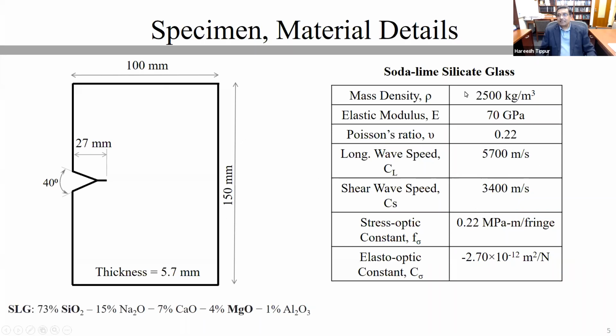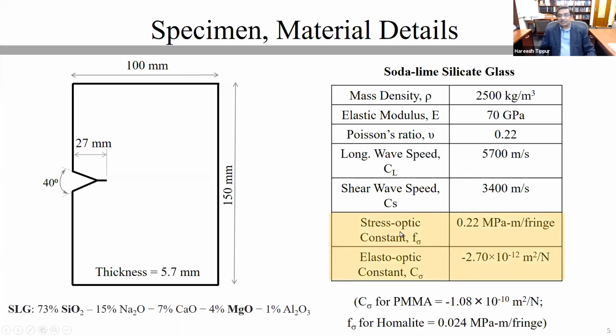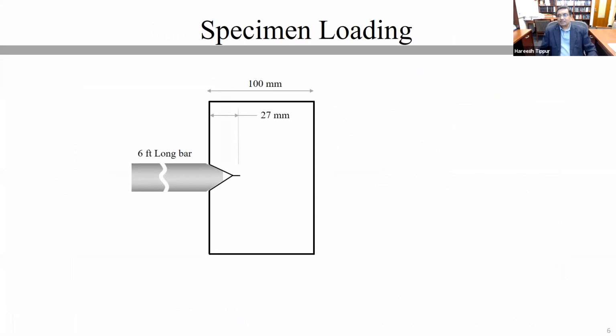The material properties that are relevant to us are the density of this material, 2,500 kg per meter cube, and the longitudinal and shear wave speeds, which are 5,700 and 3,400 meters per second. I want to highlight the stress optic as well as elasto-optic constants of this ordinary soda lime glass. Stress optic constant is about an order different from that of homalite, which is a very popular polyester using which people have studied crack branching events in the past. Elasto-optic effect is at least 50 times lower when compared to, say, plexiglass. These are the things that make studying glass extremely difficult, and people had given up on it for a long time and gone to study simply the problem using polymeric materials,